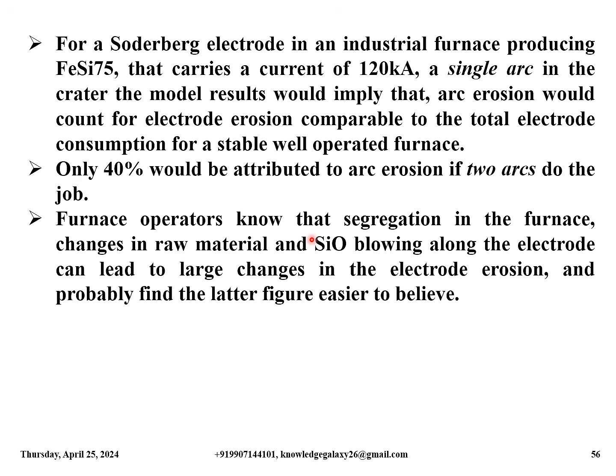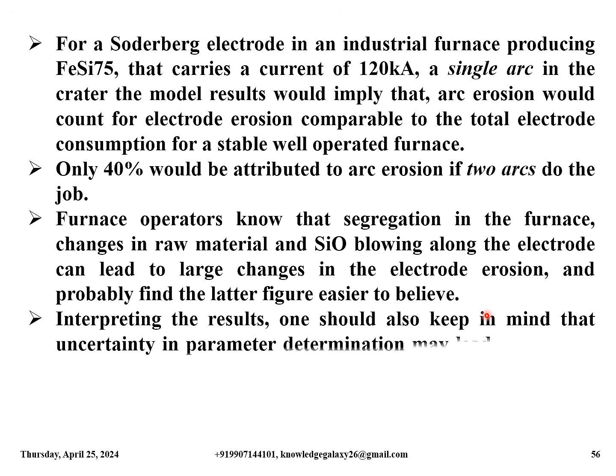Furnace operators know that segregation in the furnace, changes in raw material and SiO blowing along the electrode can lead to large changes in the electrode erosion and probably find the latter figure easier to believe. Interpreting the results, one should also keep in mind that uncertainty in parameter determination may lead to an error of approximately 30%.